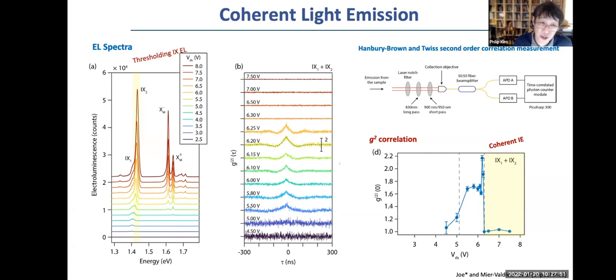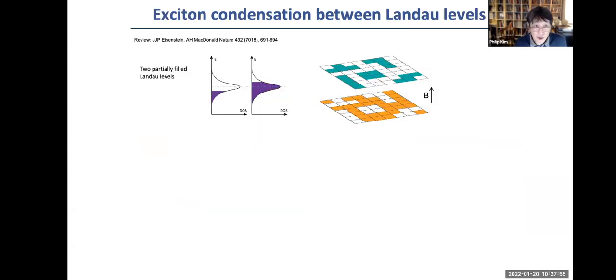It can never be achieved in these quasi-equilibrium cases. However, there is an interesting way that you can create this ground state exciton condensation, a slightly different way. In this particular example, we can still use this double layer of quantum wells, but instead of using their semiconducting gap, you can use the Landau gap, which forms by applying a strong magnetic field, which quantizes electron motions and opens up a gap in the energy spectrum.